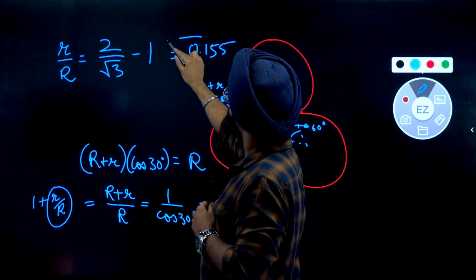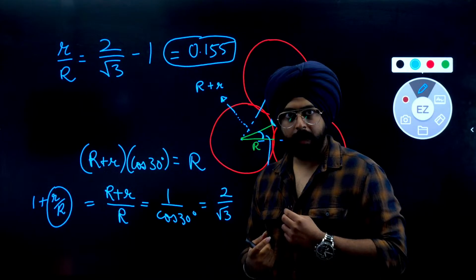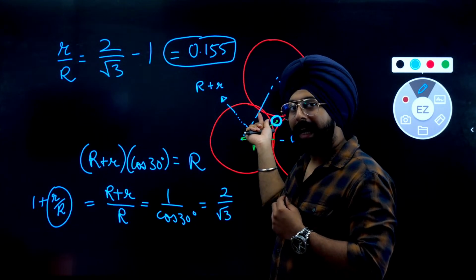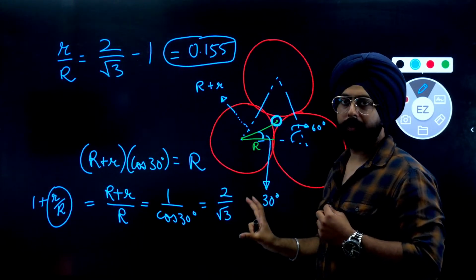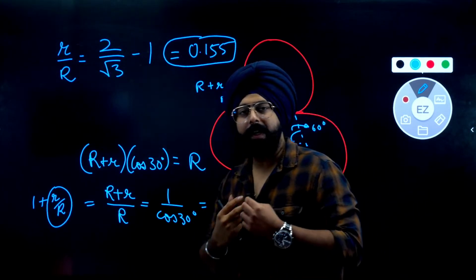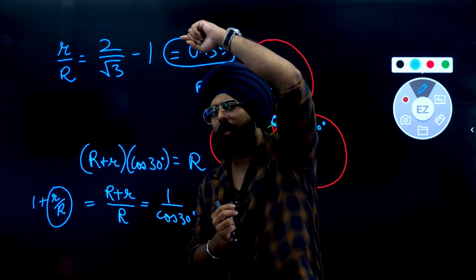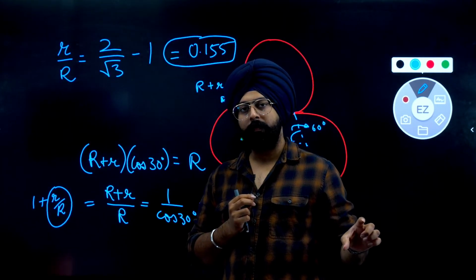0.155. Yes. It's here. So essentially, the radius of the smaller sphere over here is only 0.155 times the radius of the bigger sphere. The radius ratio of a trigonal void is 0.155. What does this mean? The English statement, the last statement of today's class.